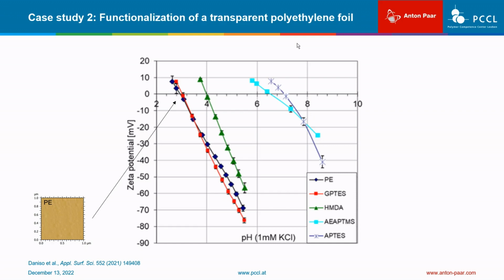The isoelectric point of the corona-treated polyethylene foil could not be detected in a reasonable pH range due to the introduction of strongly acidic functional groups, but a negative surface charge was confirmed. The polyethylene surface coated with the epoxy-treated silane exhibits an isoelectric point close to pH 3, which is the same for the untreated polyethylene foil. This silane does not introduce any intrinsic surface charge, and a similar Zeta potential compared to polyethylene is expected.